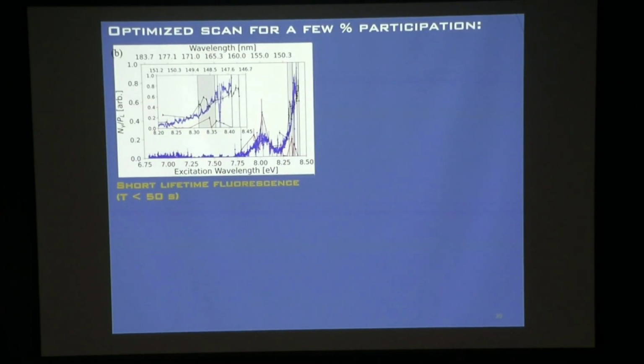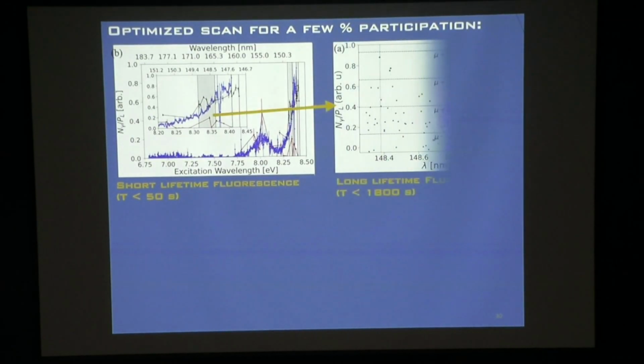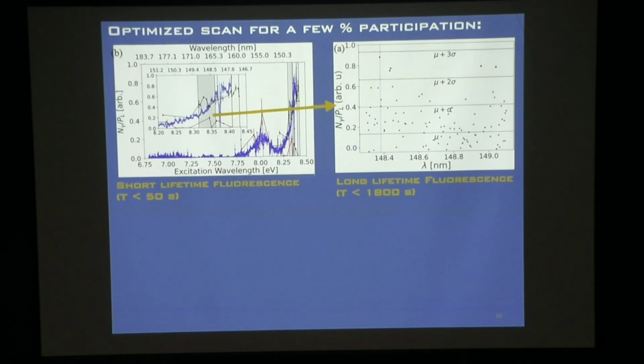So we said, okay, let's reanalyze this data differently. And this gray region is sort of where Pete said the transition should be. We said, okay, over this gray region, I don't care if we saw anything or not. I just want to know how many photons we saw in total in the 1,000 seconds after we excited. And so that's what's shown here over about a nanometer. This is the total number of photons we detected after excitation. And just to guide the eye, we calculate the mean and then draw the mean plus standard deviation plus 2 standard deviations. This is not something you're going to make any statistical claims on, so we're just trying to figure out, were there any points that were interesting?